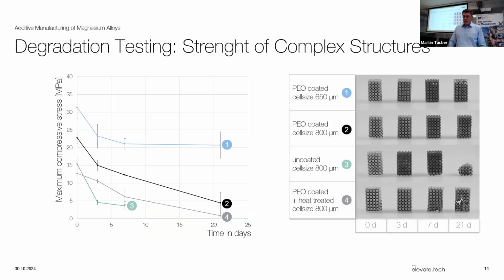We want, of course, also in the human body to have mechanical strength because the implant has to serve some kind of use, and this use is also mechanical. And here we did a small comparison by degrading samples with different sizes and different surface treatments for a certain number of days. And then we took them out of the degradation setup and did some compression testing. And on the left-hand side, you can see the compressive strength which results. On the top, you can see it's PEO coated with a cell size of 650 micrometers. The next one is also PEO coated with 800 micrometers. And below we can see uncoated samples or heat treated samples.